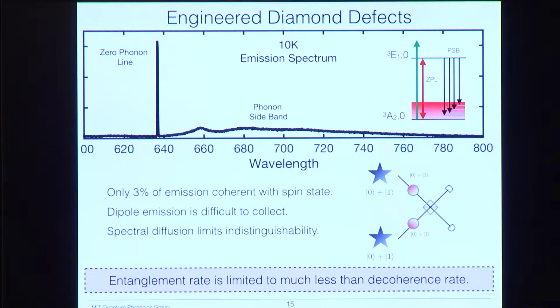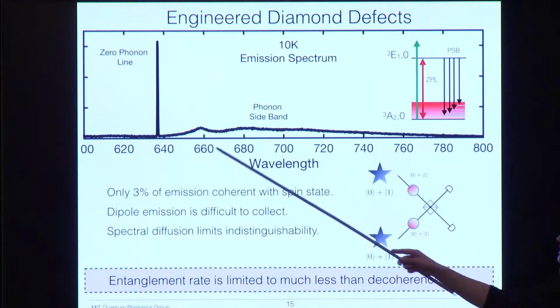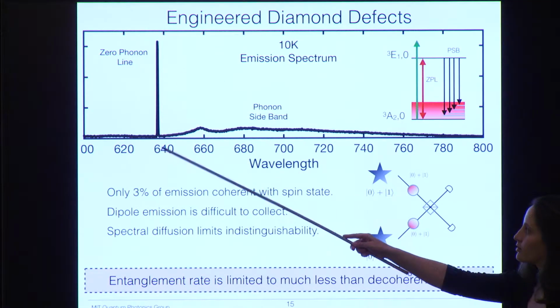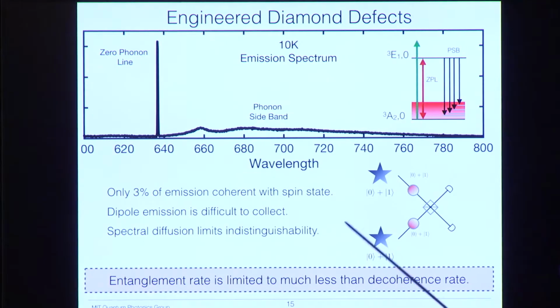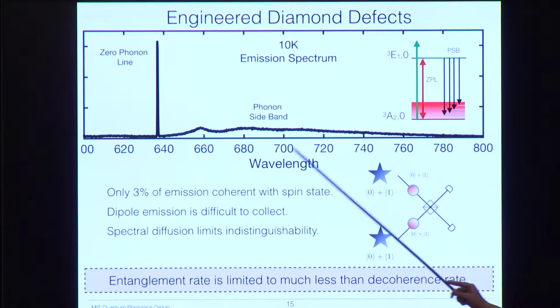So those are some good things about NVs, but there's of course also bad things about NVs. As you noticed, we really need to imprint the state of the spin with very high fidelity onto the state of this photon. However, if you look at the optical spectrum that comes out of this NV, you'll notice a few things. One, we see kind of what we'd expect, a very narrow transition. This is what we call the zero phonon line. So this is the exact transition from the ground to the excited state, or the emission from the excited to the ground state. But we also see this broad sideband, which we call the phonon sideband.